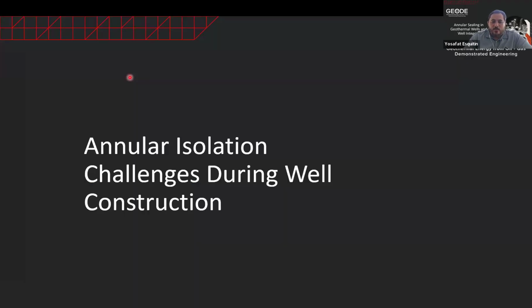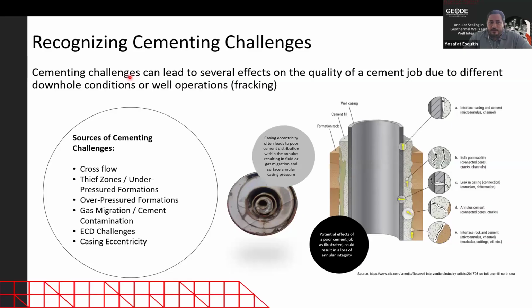So now let's look at what type of challenges exist during this annular isolation and why it's so critical to select the right type of isolation, but also do a combination of these technologies in order to have a life of well solution. So regarding cement specifically, there are multiple challenges that exist. There are challenges when it comes to life of well sealing, when cement is often subjected to different temperature cycles and pressure cycles, and then the cement gets exposed to those pressures and the expansion and contraction of cement, often leading to cement failures.